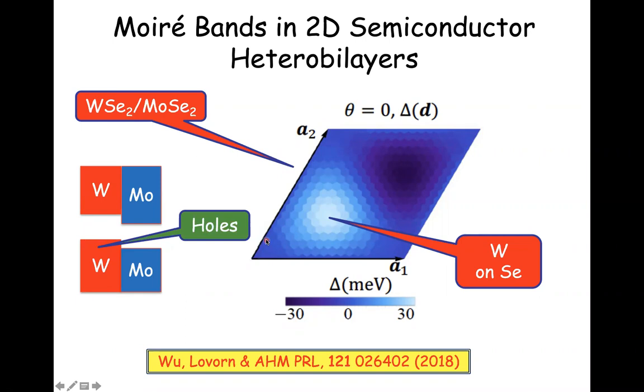It turns out that actually I lied. There are two momenta, but they're far apart in momentum space. We'll refer to them as valleys. So there's two different regions of momentum space that can be active, but because of spin-orbit coupling, there's only one state for each spin, and because spin is locked to momentum, it turns out that this problem maps exactly to particles with spin in a periodic potential. And the size of the potential is 30 meV.